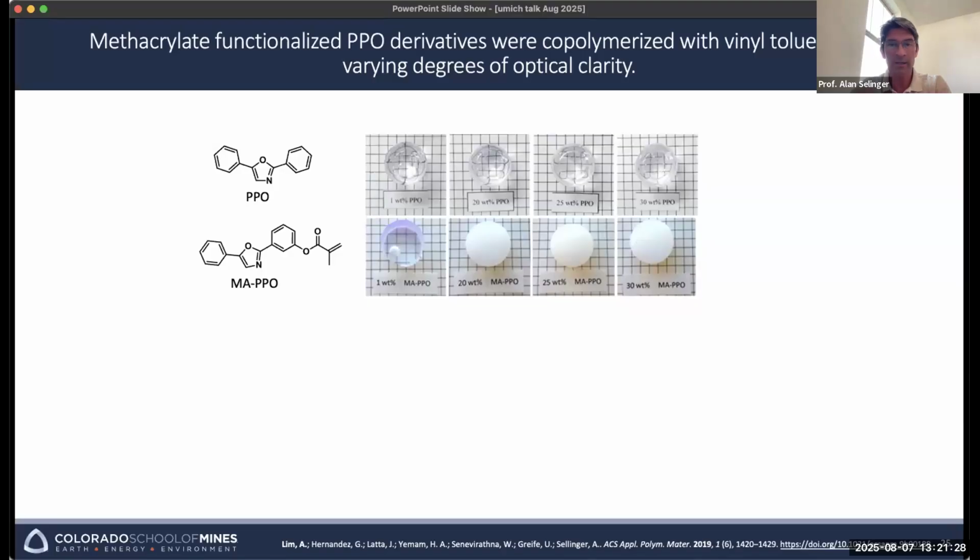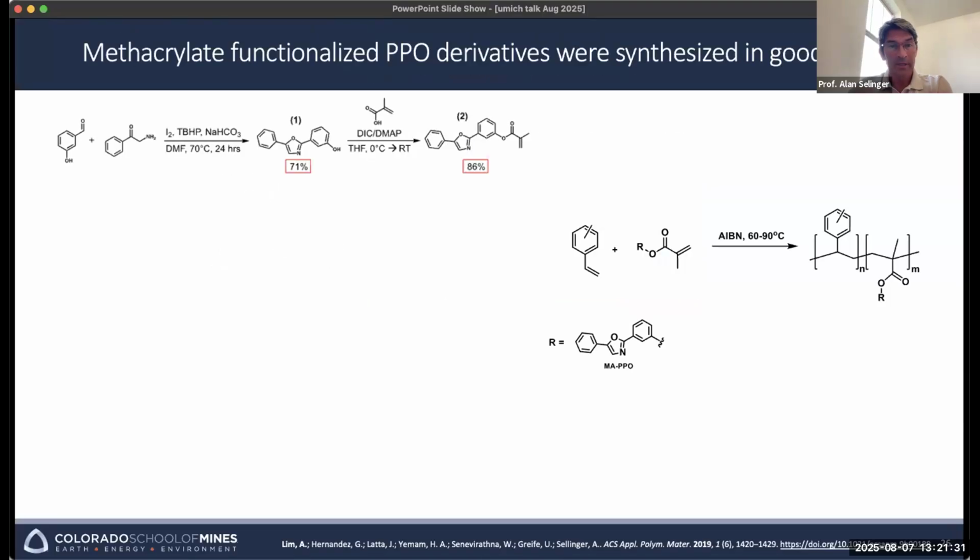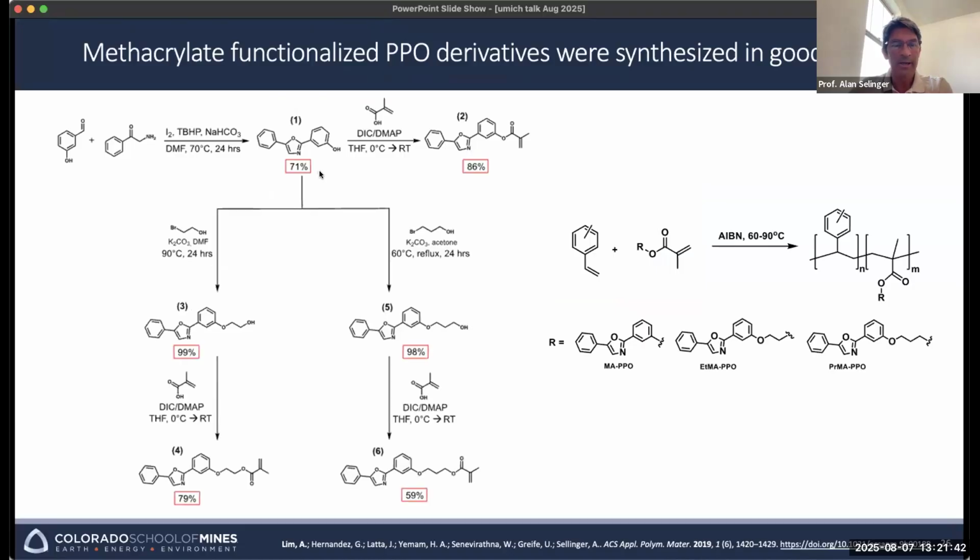So then we had to go back to the drawing board, and as chemists, we knew how to tackle this problem. And so the good thing was that we could just simply make this one precursor and then use that to generate these alternative dopants. In this case, we're adding another group on here that is 2 carbons and then the hydroxy group. Here is 1, 2, 3 carbons and the hydroxy group. And so now we're putting this reactive methacrylate out here and out here. What this does is this group is very flexible, and that will hopefully make these more soluble in the matrix.